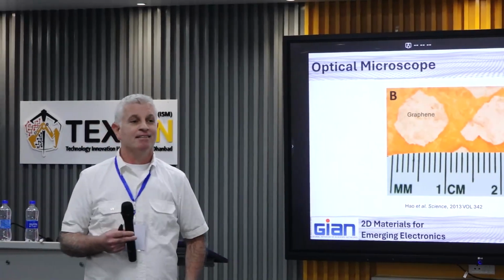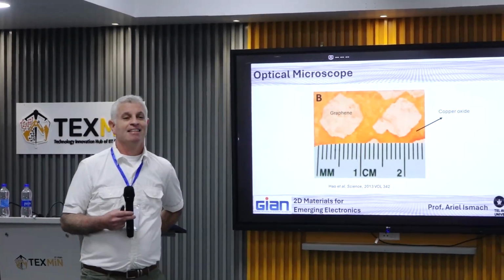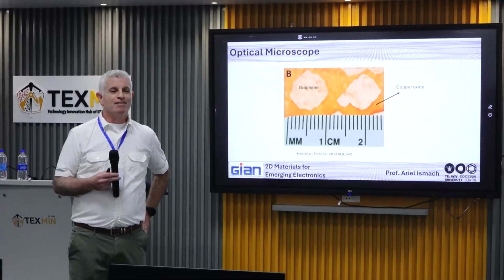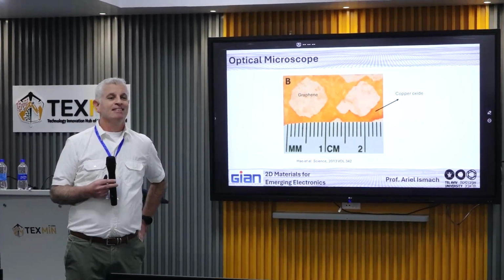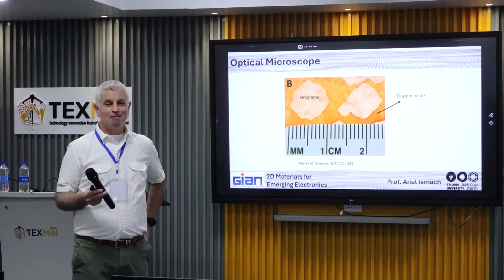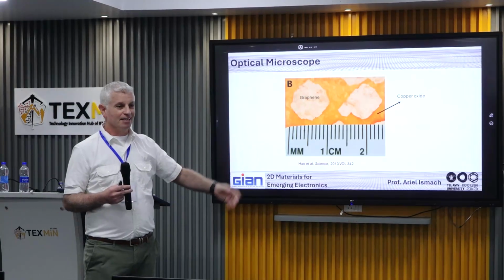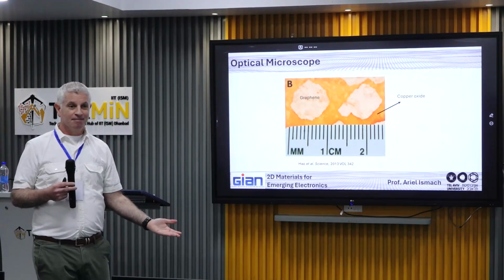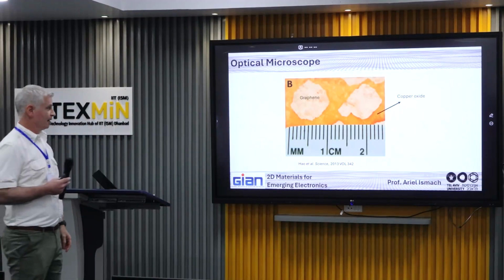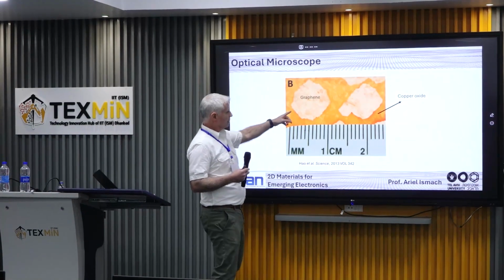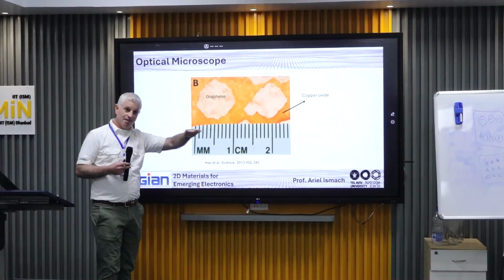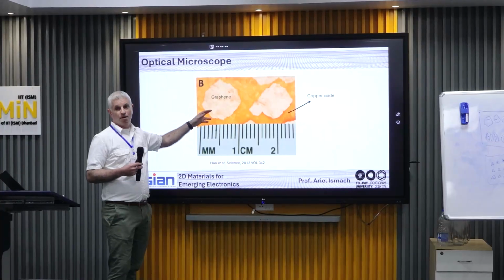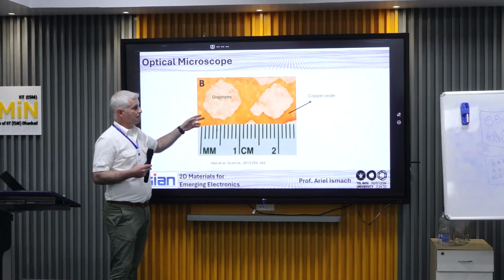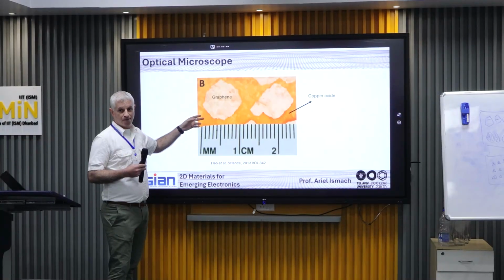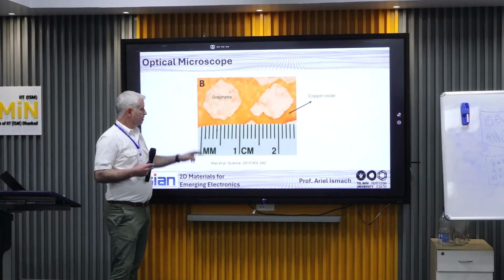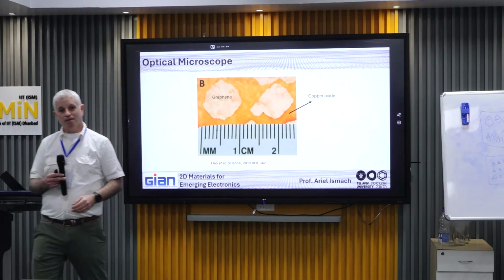Material scientists, where are they? What do you have on top of the surface of the copper, remind me? What happens to a metal when you expose it to the air? Oxide forms. So you have some oxide, and this is the reddish thing. The brighter part is the copper color, which is protected by the graphene. So oxidation is much slower. If you take the sample a few days after you synthesize the graphene, you will see something like that. And that's why you can identify where the graphene is and where not.